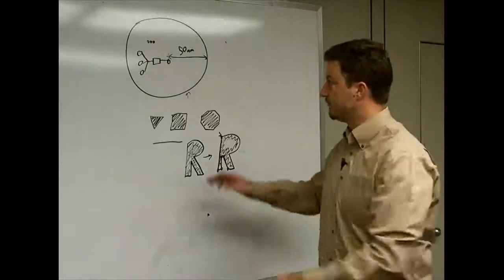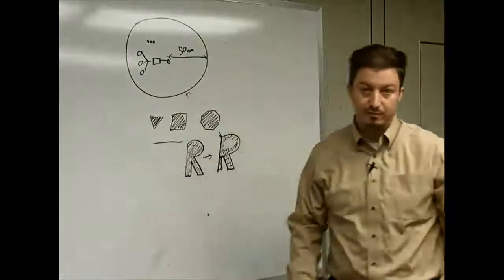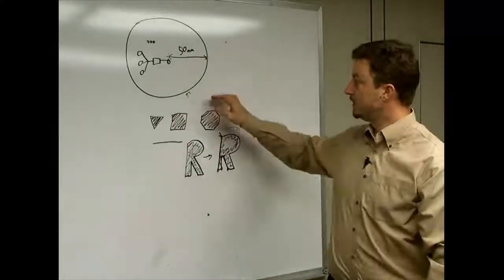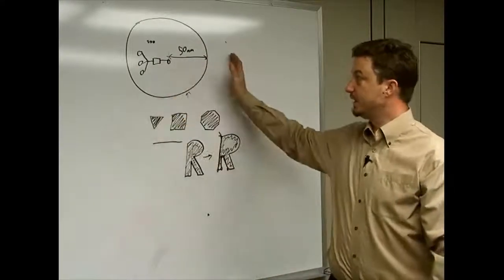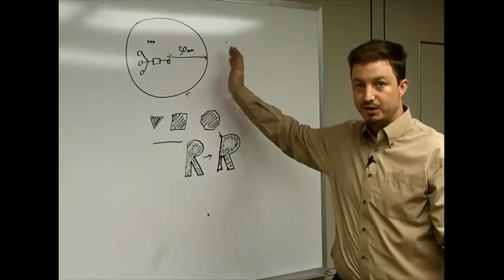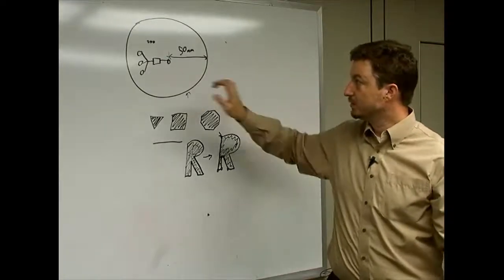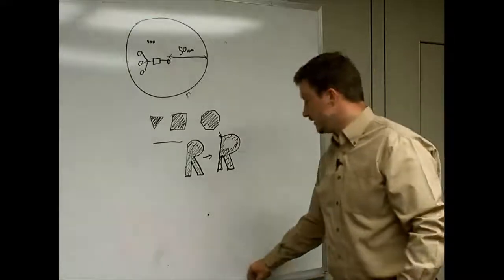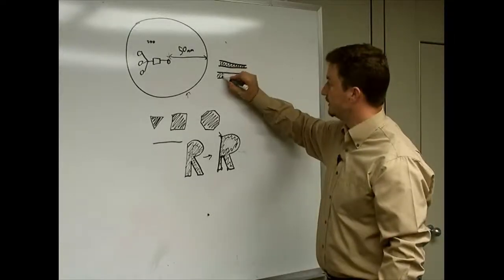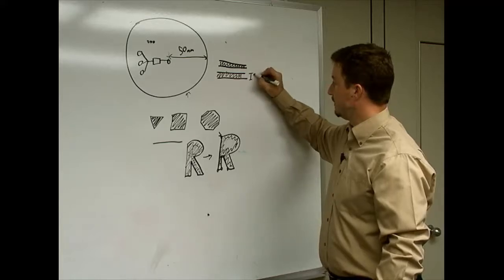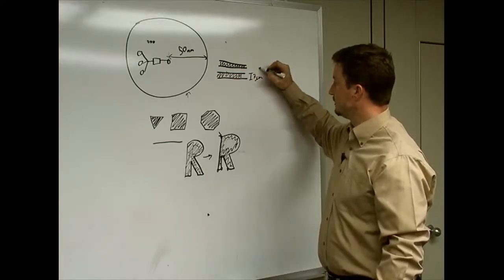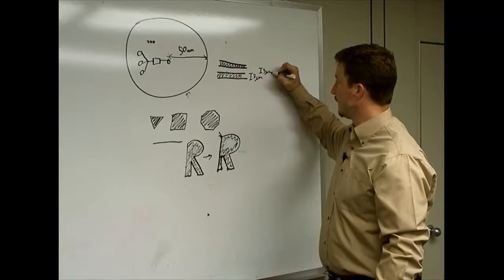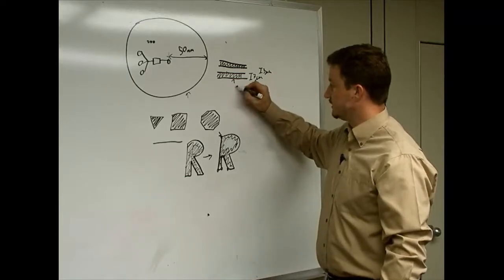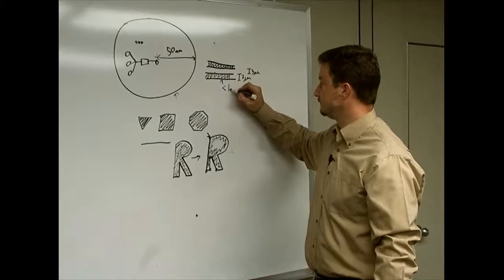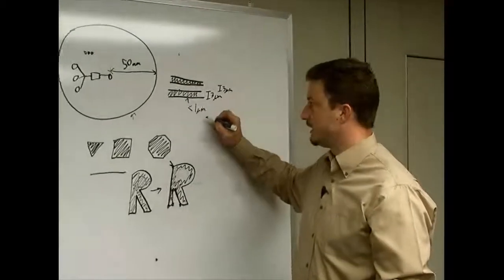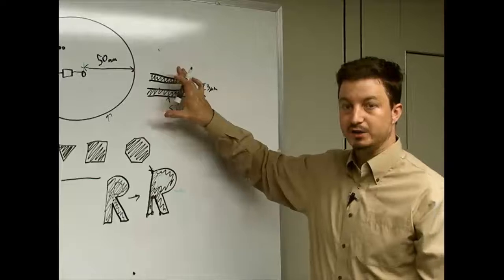The maximum write area is 101.4 millimeters for your diameter, so we can do a negative mask that's slightly larger. If you go outside that, the data will not be processed or the information will be lost. The resolution is 3 microns, so we're talking about filled polygons that are 3 microns wide, spaced by 3 microns, and the edge roughness is generally submicron, consistent with a chrome mask shop. So it really is able to do high resolution.